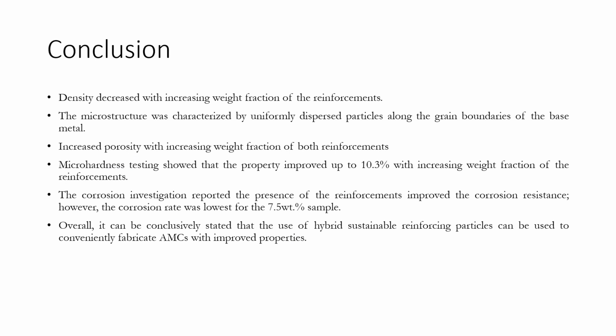So in conclusion, this work was done to investigate the effect of aluminium alloy 6063 reinforced with eggshells and fly ash. The work showed that the density decreased with the increasing weight fraction of the reinforcement, which suggests that the utilization of this hybrid reinforcement can produce lightweight aluminum matrix composites.